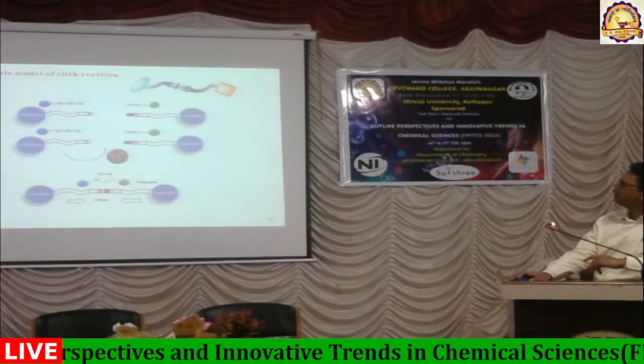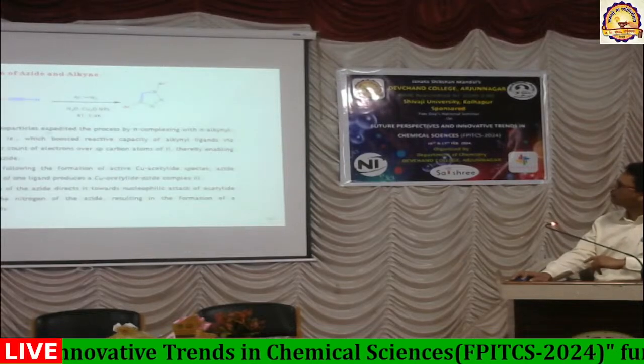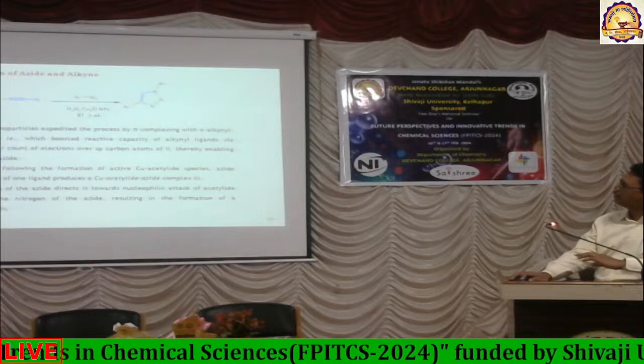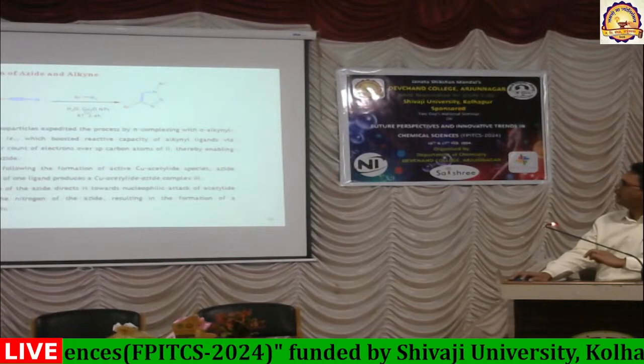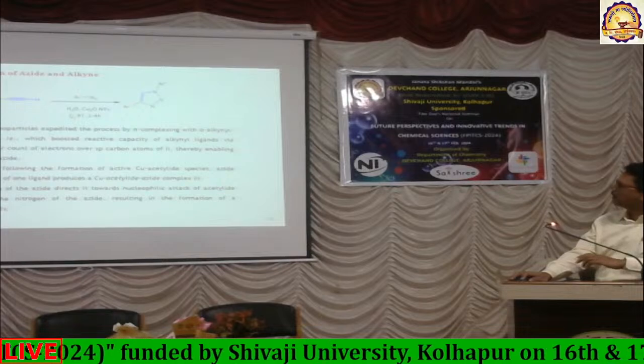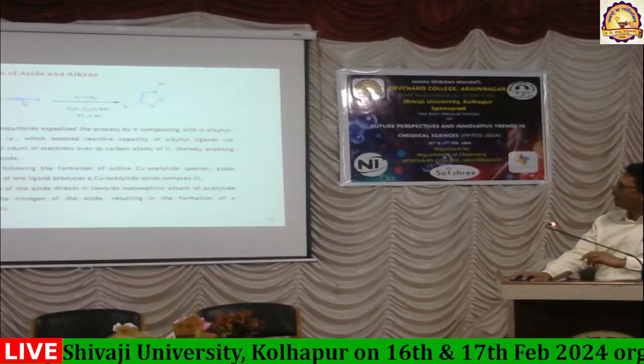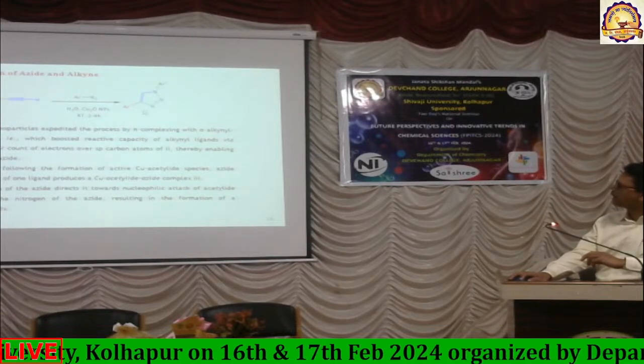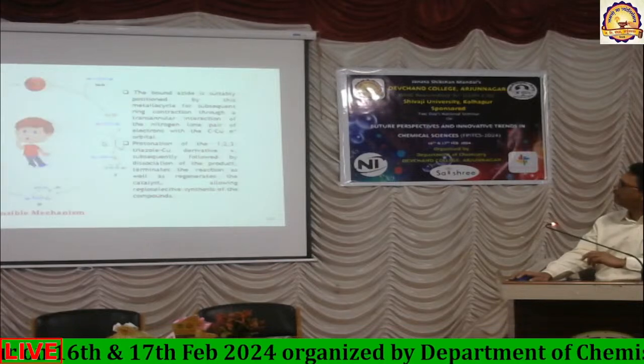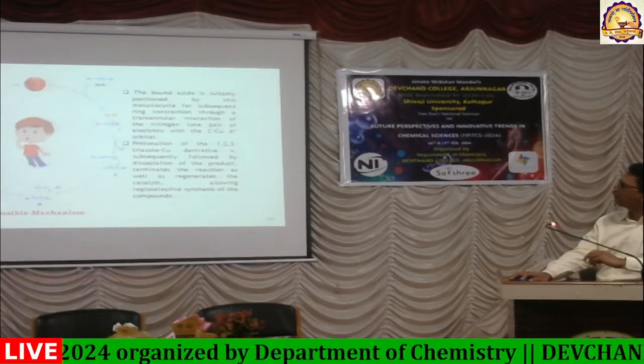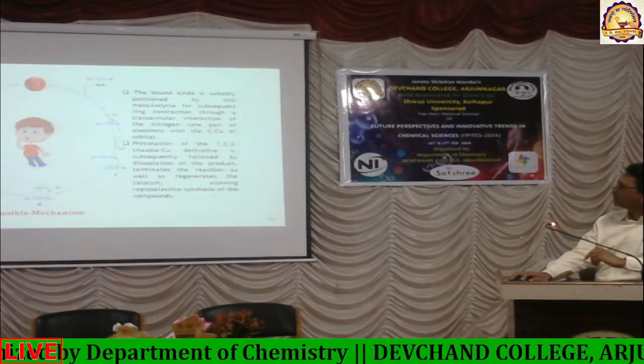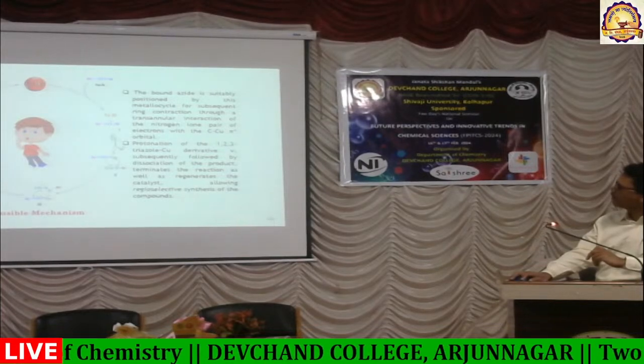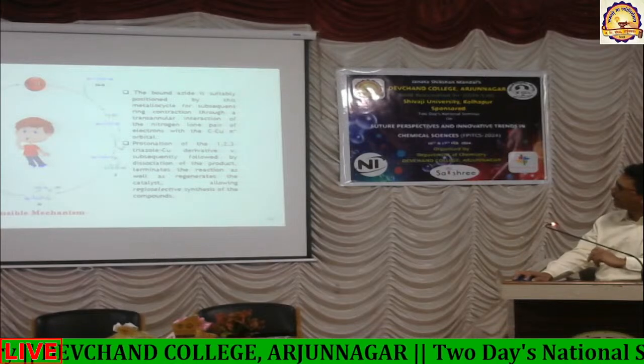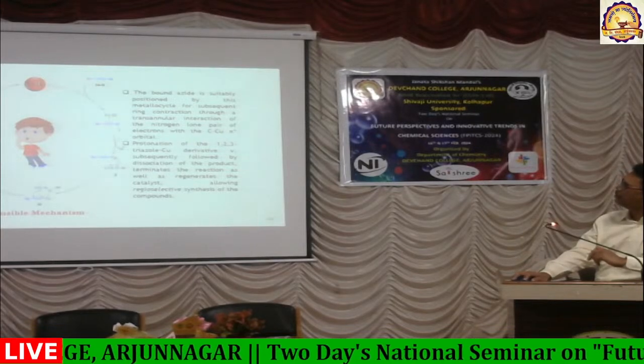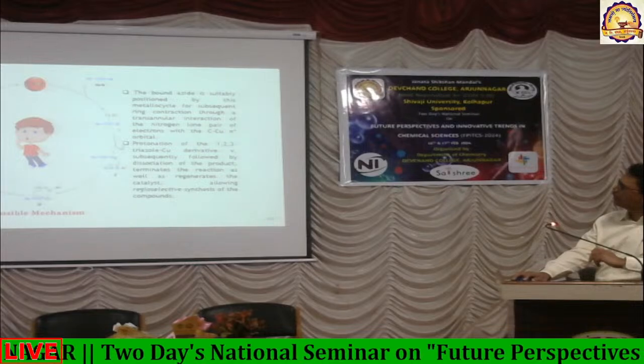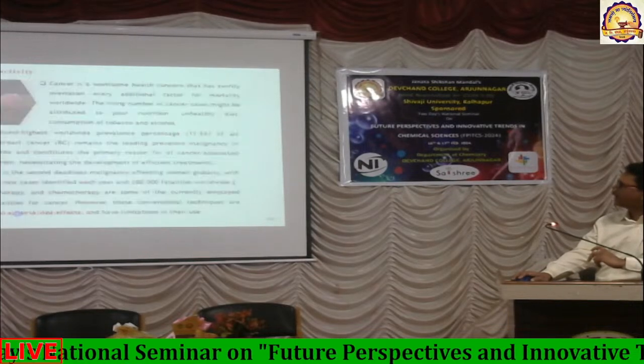So this is once again a copper oxide nanoparticle that we synthesized. What we did was make use of these copper oxide nanoparticles, because in the earlier example they used copper sulfate as a catalyst for the conversion of alkyne and azide into a 1,2,3-triazole, and we even gave a mechanism where the copper forms an intermediate with the lone pair, the pi electrons of this alkyne, and a metallacycle is formed, and at the end there will be conversion of this into a triazole. We even proposed a mechanism for this.